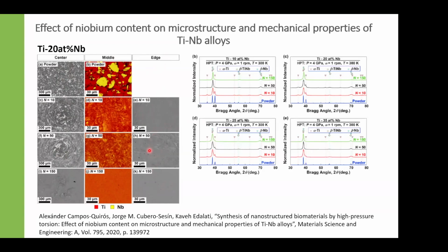As I said, the strain will depend on the radius. So usually the material at the edge will evolve faster and will have a very small grain size. We did XRD, and we confirmed after 150 turns, the microstructure is fully beta phase because of the characteristic peaks, and we see the gradual disappearing of the alpha titanium peak. Even after 10 turns, we don't see it in this composition or this composition. A little bit still at the 25% and 35%, but then gradually after 150 turns, we are fully beta phase, and this is also a nanocrystalline material with a very small grain size. I will show a couple slides of the microstructure of a similar alloy, but the grain size here is something like 30 to 50 nanometers. It's a very small grain size crystalline material.